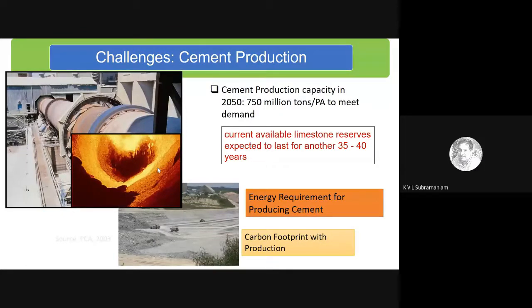So we have to look at reducing the amount of clinker in cement, because remember, clinker is the one that basically comes from the use of these raw materials. Although the energy requirement of cement is less compared to the other construction materials, if you look at the large volume in which cement is required, we have to address the energy issue. We have to look at consuming less energy in making cement, and the carbon footprint. It is the second largest or the third largest anthropogenic source of carbon dioxide. We have to address this issue.